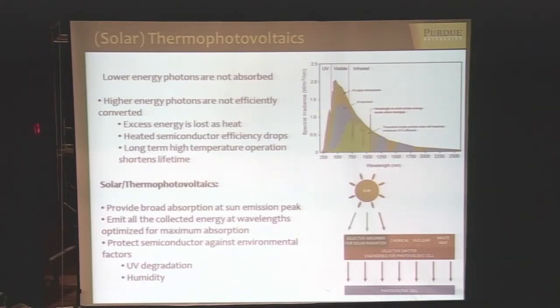It's also well known that if you do it a different way—just heat your object up to high temperatures, let's say 1500 Celsius, and let that black body radiate, using a frequency-selective emitter so it emits only the wavelengths which match the gap of your photovoltaic cell—then the efficiency could be much higher. Theoretically, it could be 85%. It's a fact known for decades. The problem was the materials which would enable this type of energy conversion.